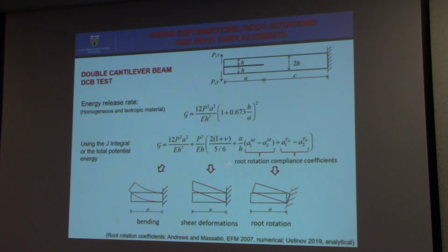But then we have a contribution from shear deformation along the beam, and then we have two additional contributions which are due to these localized root rotations. And we have root rotation produced by the bending moment at the crack tip and root rotation produced by the shear forces at the crack tip. And these coefficients, as I said, can be found in the literature. They've been tabulated for different material systems and different positions of the crack. So we can now use them with confidence. And as I said, they've also been verified analytically recently by Konstantin Ustinov.